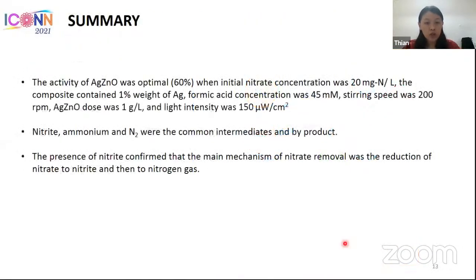So this is the summary of my whole presentation. The activity of silver zinc oxide was optimal, where we reached 60% nitrate removal when the initial nitrate concentration was 20 milligram per liter, and the composite was in the presence of 1% weight of silver, with an initial formic acid concentration of 45 millimolar, stirring speed at 200 RPM, silver zinc oxide dosage of 1 gram per liter, and light intensity of 150 microwatt per square centimeter.